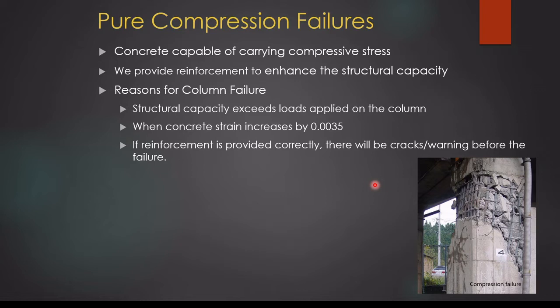Pure compression failure: when a column is subject to pure compression, there could be chances of failure. When there are no major movements, there won't be any deviation in the stress in the column — basically the stress will be uniform with no deviation, and that is only an axial stress. Now according to BS standards, reinforcement yielding strain is considered at 0.002 and concrete ultimate strain is considered at 0.0035. Reinforcement yielding occurs before it reaches the concrete strain at which it fails.